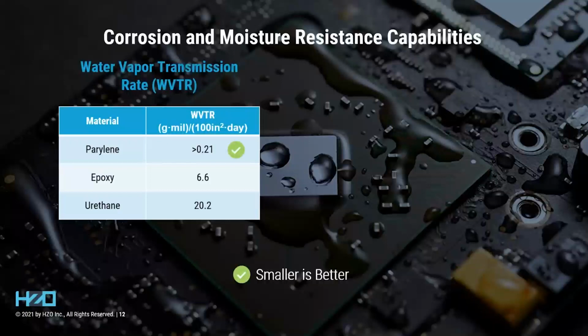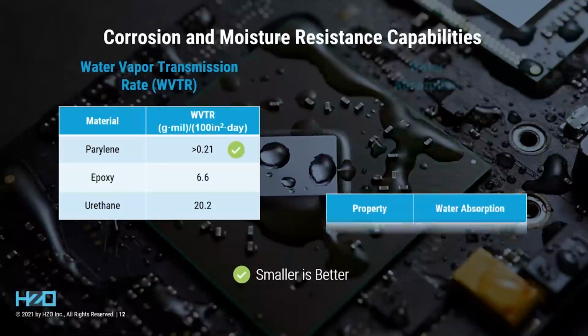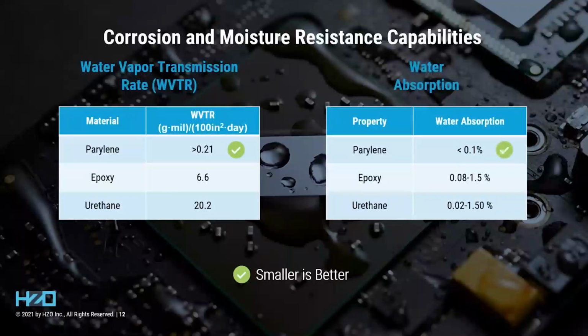The second corrosion property we worry about is water absorption. This plays a role in overall corrosion protection. It also affects your RF and wireless designs and performance. So when your dielectric coating on the outside of your antenna starts to absorb water, it can affect your RF properties. What we want is something with a very low water absorption rate. Parylene does this in spades and achieves a lot of what we're after here.